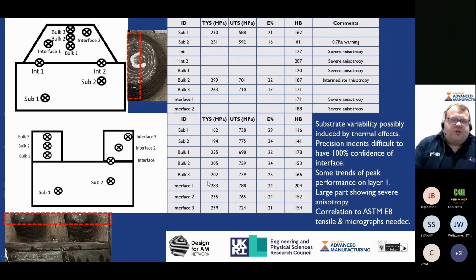In the case of the large cylindrical part, there was quite a lot of distortion on the build plate. It was an inch thick substrate as well, and we still had some significant distortion. I do believe the organisation who helped us with this found a couple of parameter issues in that part in the end. But we did see quite severe anisotropic performance in those interfaces in particular. We also have quite a different performance as we move up from the substrate into the weld material in both cases. That substrate variability, when you look at the different performances from the substrates of the two parts, is potentially because of the thermal effects of that large cone area.